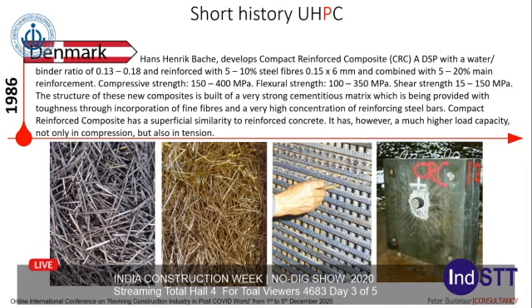In 1986, Hans Henrik Bache developed compact reinforced composite, a UHPC with a water-binder ratio of 0.13 to 0.18, reinforced with 5 to 10% steel fibers and combined with 5 to 20% main reinforcement. Compressive strength 150 to 400 megapascal. Flexural strength 100 to 350 megapascal. Shear strength 15 to 150 megapascal.